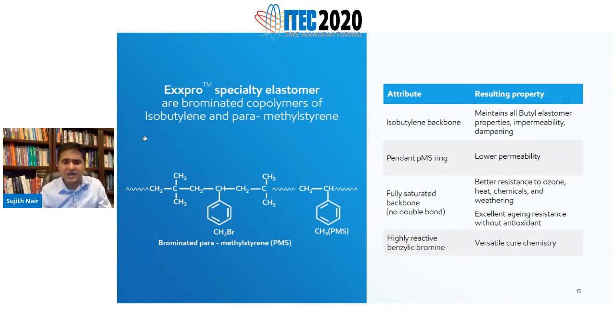We already talked about the fully saturated backbone, no double bonds in the main chain, gives it very good resistance. And then the other thing is that all the cross-linking happens through that CH2Br moiety that's on the bottom of that aromatic group. And that's how you get your cross-linking. So what happens because of this is you can actually have an avenue for a very flexible cross-linking. You can cure the material without sulfur. You can cure it sulfur-free. So that's what we call clean cure systems.